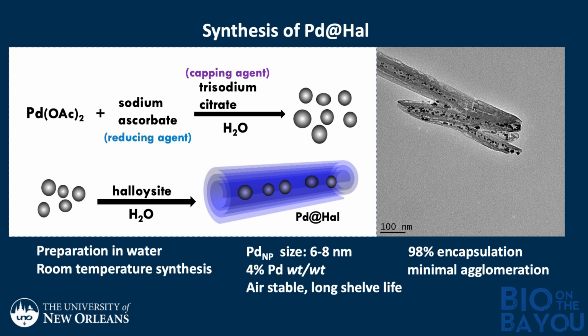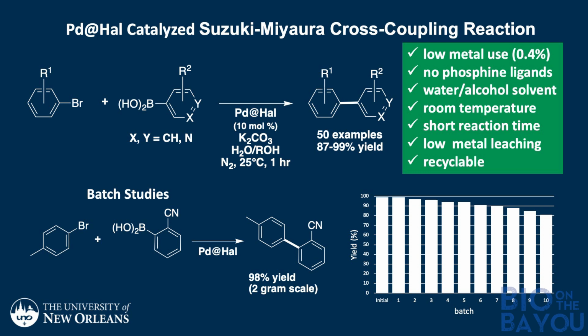They enter into the tube in water, and basically we get this nanocomposite, which here we have a TEM image. You can see the little nanoparticles inside the tube. And this process gives us about 98% encapsulation of the metal. Overall, it's about 4% weight by palladium based on the material. But essentially, this gives us an air-stable material that it turns out is highly catalytic. Now, when we applied this to essentially some Suzuki coupling reactions, we found that we could catalyze the reaction quite nicely with low metal content, basically about 0.4% metal.